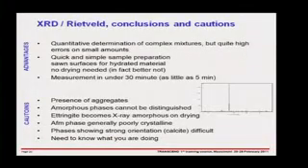You can even just saw your surface, but again, there are limits to that. And if you make a powder, you have to be very careful of how you pack it into your sample holder, because it's very easy to get effects of preferential orientation.